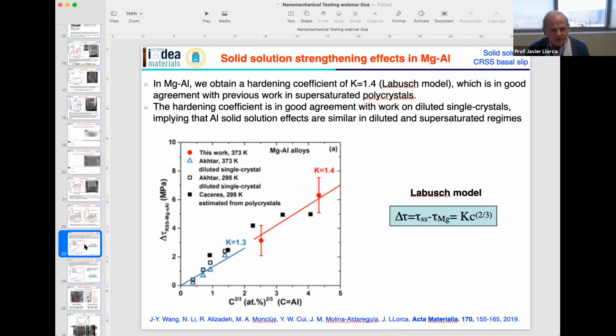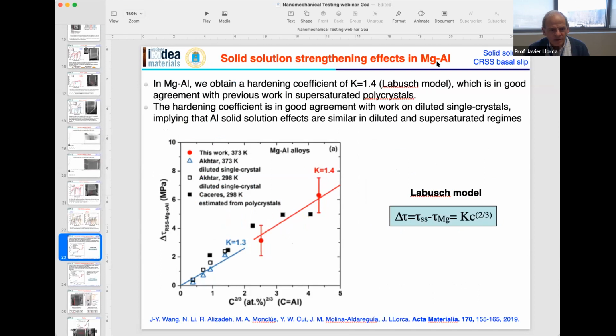This is a summary of the results we obtained for the solid solution strengthening effects in magnesium aluminum. This is the increase in the critical resolved shear stress as a function of the aluminum content. The black solid and open symbols are results from the literature. There are very few data from the literature. This corresponds to the results from Akhtar here, and this corresponds to Cáceres in another study, in this case in polycrystals. These are tests in all cases at 100 degrees Celsius, and the red lines are our experimental data.